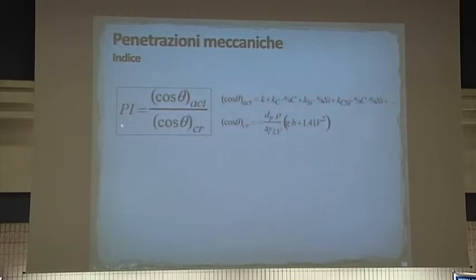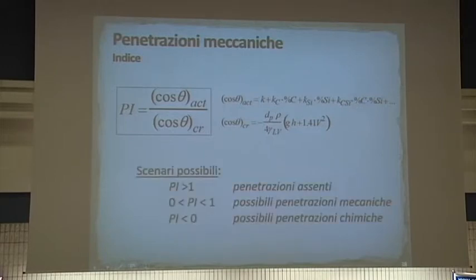And we have the penetration index, which is a ratio between the critical angle and the actual contact angle. The actual contact angle is the contact angle of your metal, which is a function of composition and a function of temperature. If this index is higher than 1, you have no penetration. If it's in between 0 and 1, you have mechanical penetration. If it is smaller than 0, then you have chemical penetration.